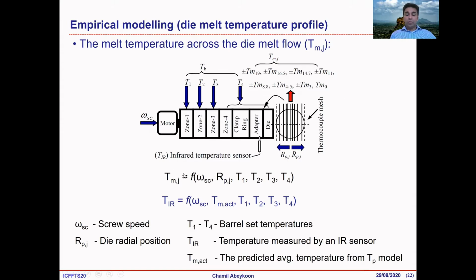We recognized that the key parameters which decide the melt temperature of the extrusion process are the screw speed, the radial position across the die, and also the set temperatures of the barrel. So these are the key parameters. Apart from these, we have other material parameters like density and viscosity, but at this stage we did not add them. This can be added later. So this is the structure of the model to predict the melt temperature profile that we decided at the first stage.